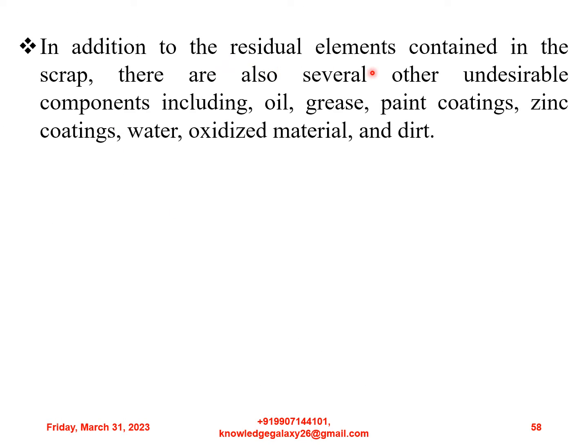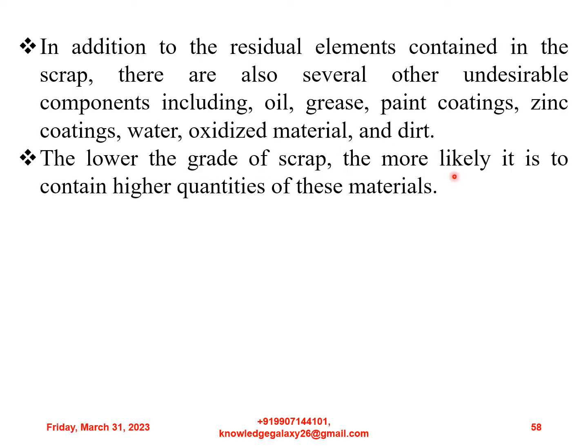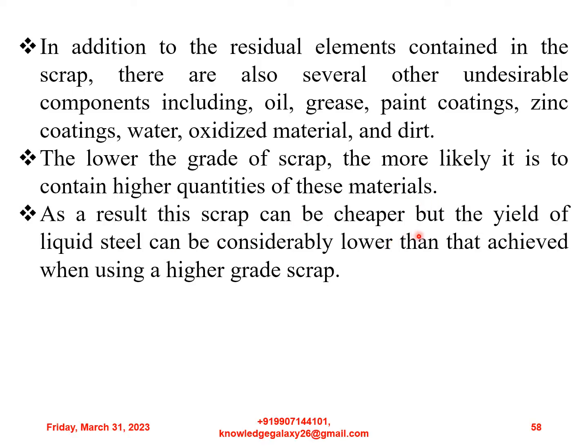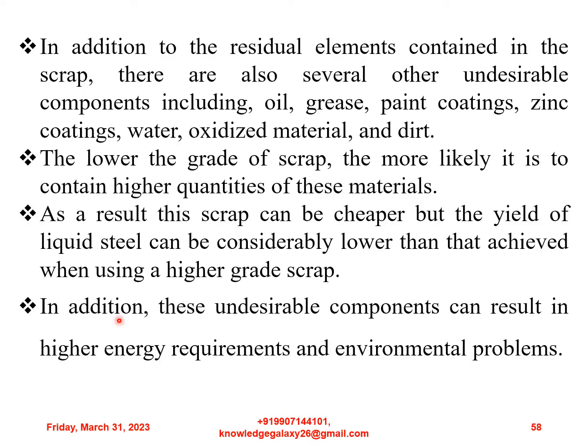In addition to the residual elements contained in the scrap, there are also several other undesirable components including oil, grease, paint, coatings, zinc coatings, water, oxidized material and dirt. The lower the grade of scrap, the more likely it is to contain higher quantities of these materials. As a result, this scrap can be cheaper, but the yield of liquid steel can be considerably lower than that achieved when using a higher grade scrap. In addition, these undesirable components can result in higher energy requirements and environmental problems.